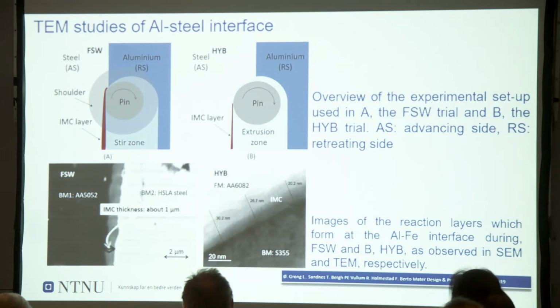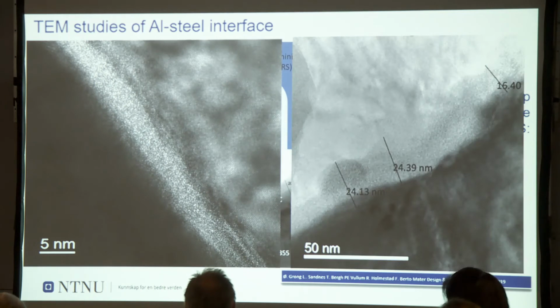And if you consider the TEM studies of the interface and you measure the intermetallics, what is important to note is that for traditional friction stir welding, we have an intermetallic that is usually 1 micrometer. And this is critical because sometimes the cracks propagate from the intermetallics and cause the failure of the components or of the bonded connection from there. But if you look down in scale, in the hybrid, sometimes the interface is very sharp and it goes to 5 nanometers. And in other cases, it reaches a maximum of 25 nanometers, which is quite impressive.